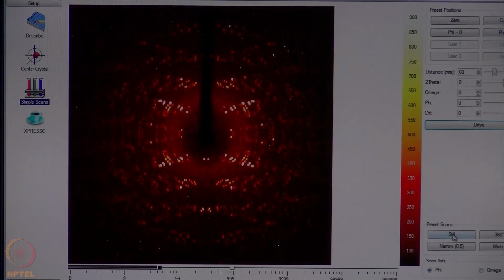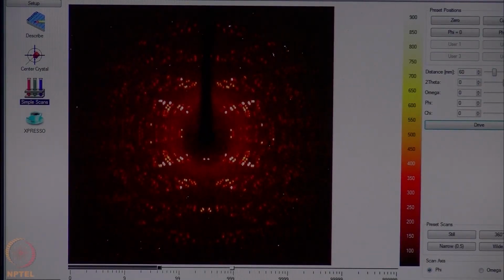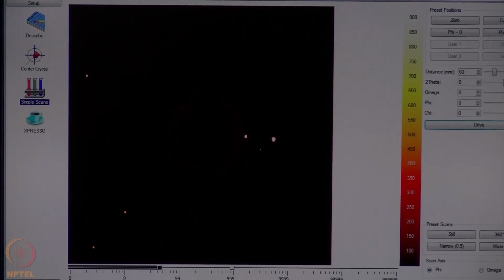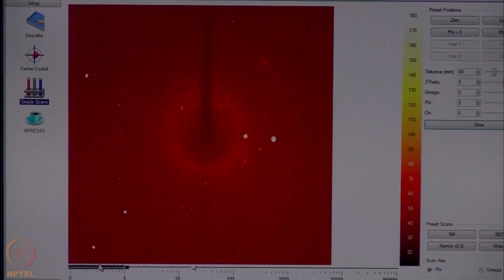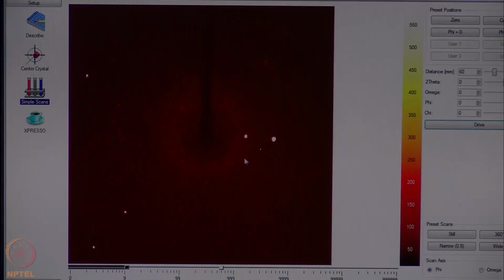So to decide on the exposure time, we should take a still photograph with say about 10-second exposure time and see how the crystal is diffracting. If it gives reasonable spots with 10-second exposure, we will collect the initial frames with 10-second exposure. If it does not give good diffraction with 10 seconds, we may have to increase it, or if it is too intense, then we have to decrease it. So here what we can see is that the crystal is diffracting reasonably well with this 10-second exposure, and the spots are nice and circular. So we will use this 10 seconds as a standard for getting the unit cell measured.